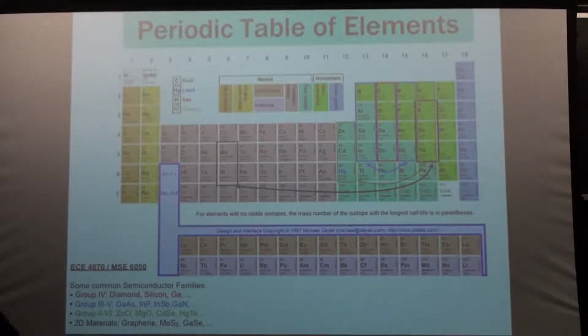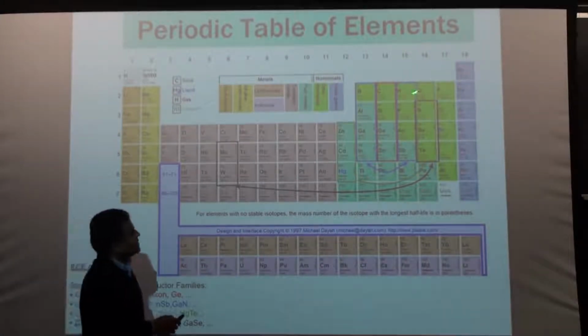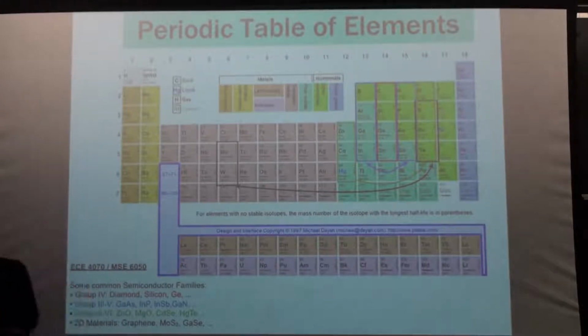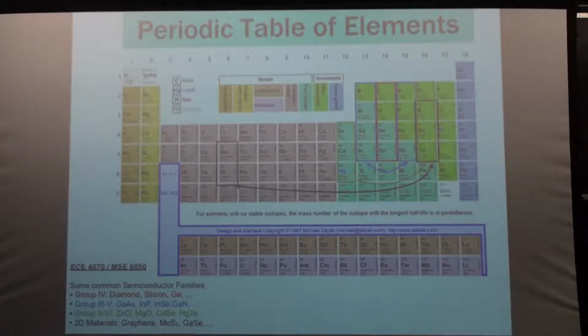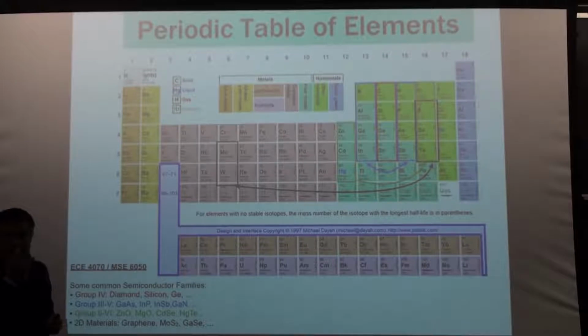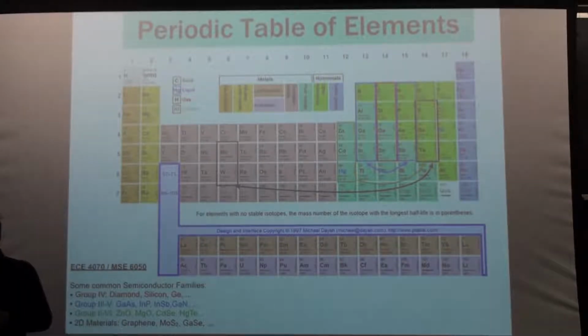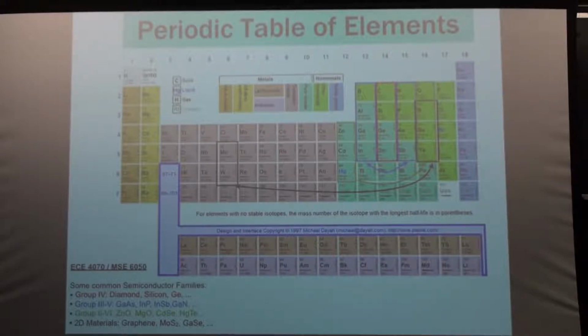And similarly, group 2-6, zinc oxide. Zinc oxide has a gap of 3.3 electron volts. One of the interesting things about zinc oxide is it can occur as nanoparticles. You can easily synthesize them, and then we put it in an ointment, and that's your sunscreen, right? So it absorbs UV light because its gap is 3.3 electron volts and UV light is slightly more than that. So probably that's the widest or highest volume usage of this material.